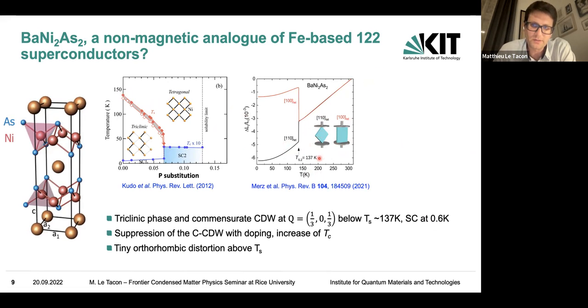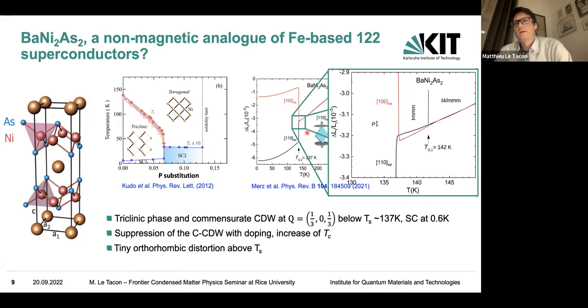So basically, what Christoph does is that he looks at the change of the length of the sample upon cooling, and you see that when you go to the triclinic first-order transition, there is a huge change, a relatively large change, say, of the 100 direction against the 110 direction. But if you zoom in, you see a very tiny difference occurring just above. So upon cooling, it's at 142K, and that would look more like a second-order transition, because the first one looks first order.